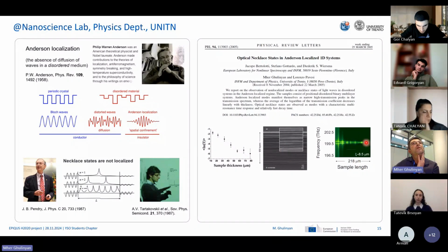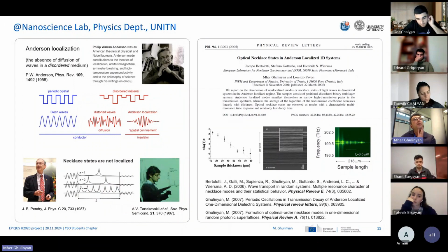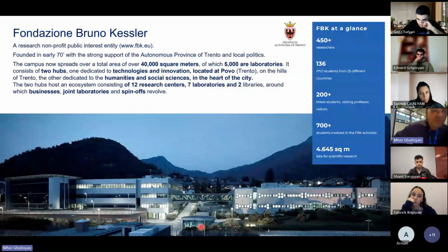And this was explained by the very occasional formation of several identical cavities within a random structure. You have to remember that this is a random structure, so you do not design coupled microcavities. You design a series of random structures, but at some point strange cavities are formed, and you cannot predict their formation, but you can get a resonant state between different ones. They call them necklace states because the wave functions are coupling like this and form a kind of necklace. We did several other publications about this. And now I'm ready to speak a bit about integrated photonics.